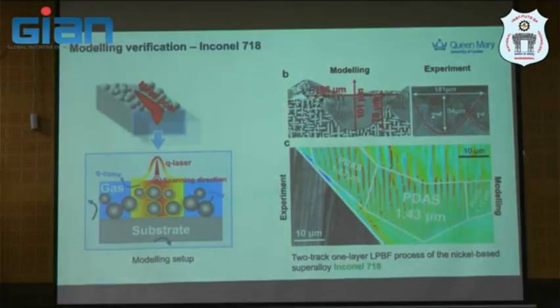But what we got here is actually dendritic. If you remember yesterday, Hong Hao presented this, this is what we can predict. It's 3D, but a thin slab of 3D, represented with fluid flow in the 3D model. And you see, this is prediction, not experiment. The predicted structure here, in terms of dendrite arm spacing, is so similar to the melt pool in the experiment. And when we look closer at this primary dendrite, you will see the spacing is on the 1 micron scale.